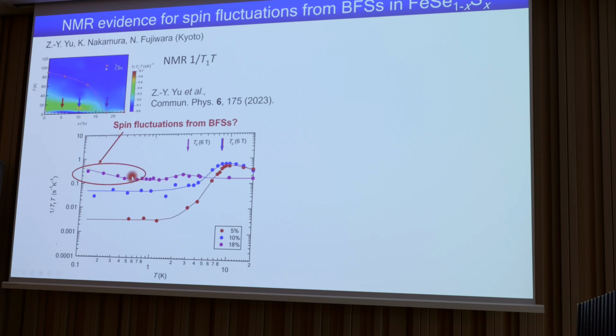That indicates that we have some kind of spin fluctuations present even in the superconducting state. But usually if you have a superconducting gap, the Fermi surface is gone, so you don't have a spin fluctuation.